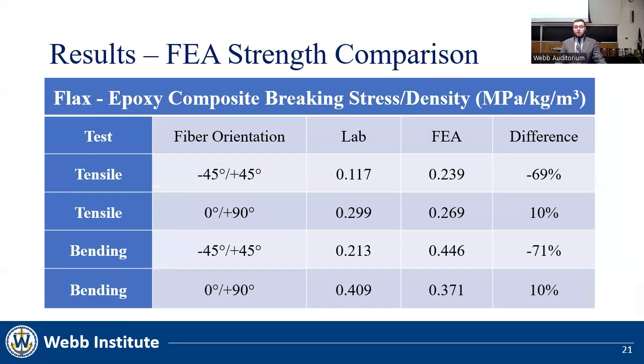Before I discuss these results themselves, it is important to note that the physical flax epoxy composite is only 25% as dense as the predicted value that was used in the finite elements analysis. So to give a better comparison, the breaking stress was divided by density to show the strength per weight of the composite instead of the strength per volume. Error with the 45-degree fiber orientation is due to the law of mixtures, as it does not accurately predict the strength at an angle from the fibers, since it is a laminate composite instead of a homogeneous composite. The same trend can be seen here with the bending test.